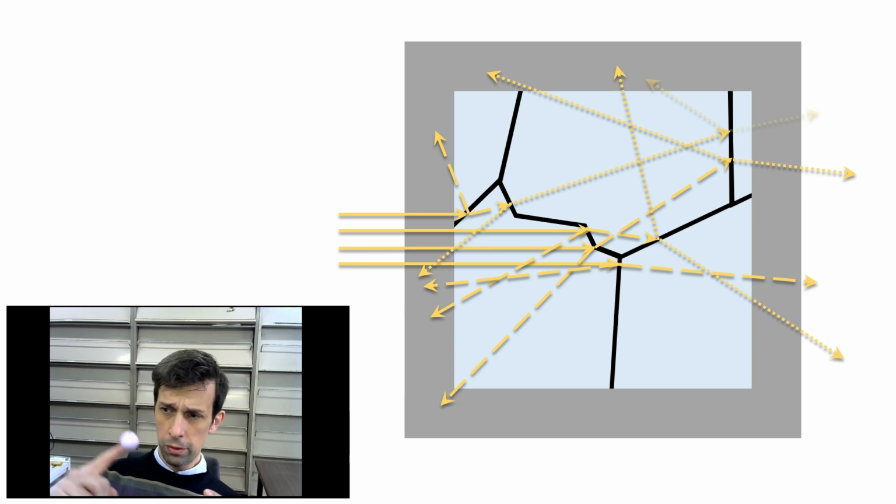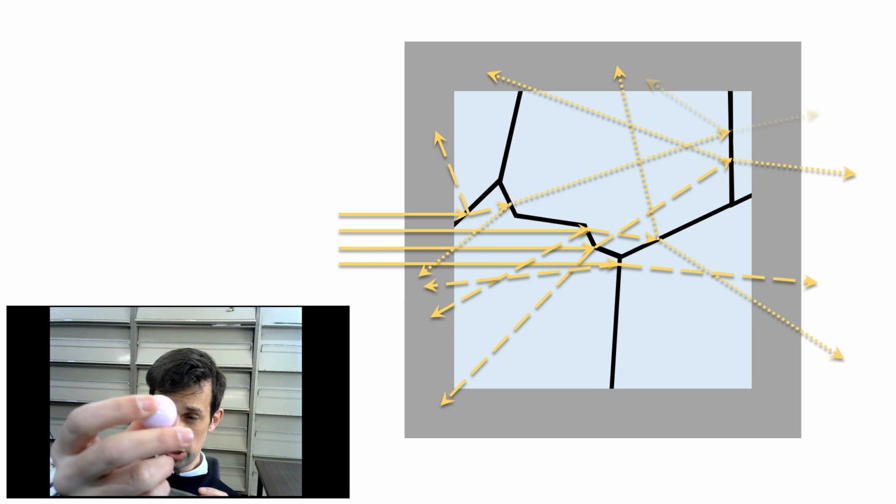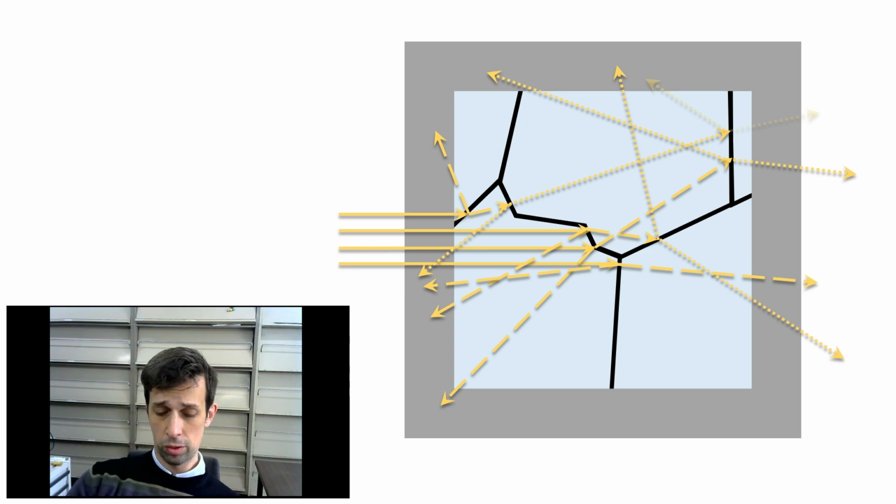And if you look at this, this is a femoral head. It's pink, and it's basically a ruby. The reason why it's not transparent and shiny and red, with a strong red, is because it's a polycrystalline ruby. If it was a monocrystalline one, we would have transparency and a stronger red color. Instead, we got this nice pink. Okay.